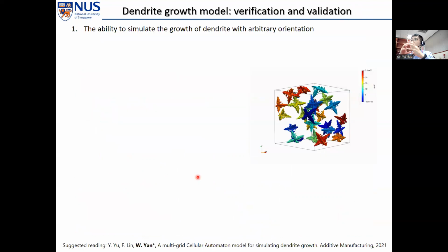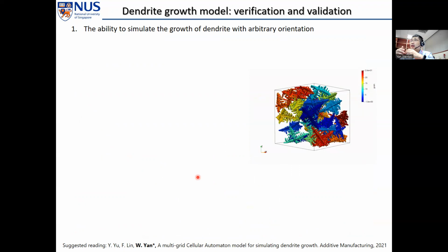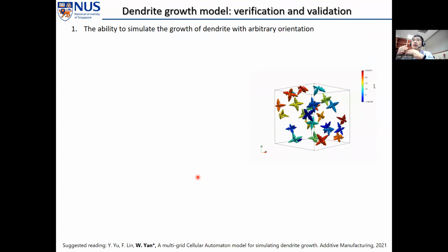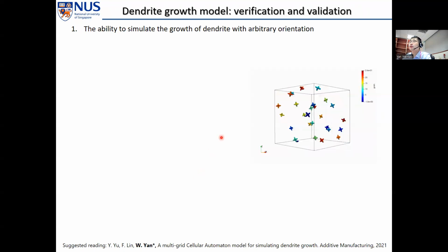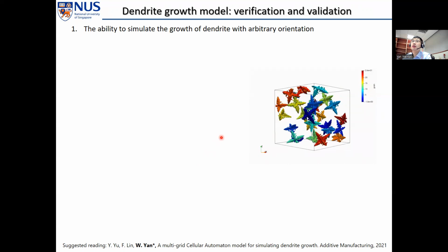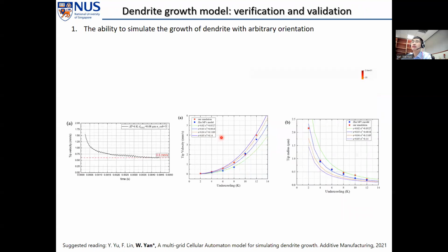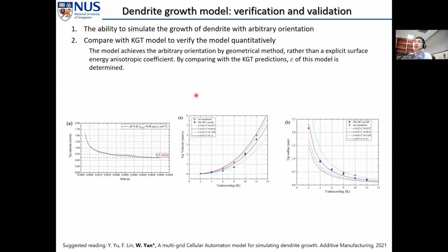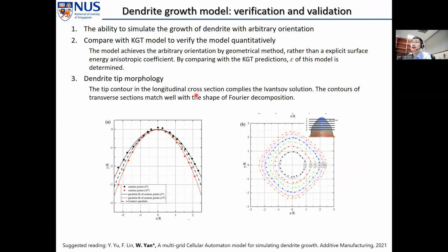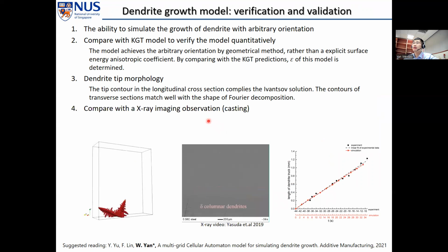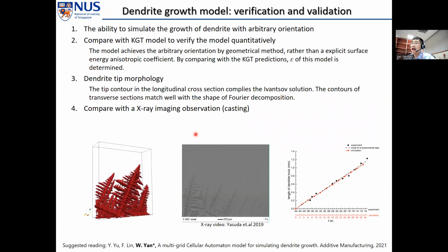But for even smaller scale, in dendrite scale, that is where the solidification defects happen. So to do that, we develop a new model to simulate the dendrite growth with arbitrary orientations. And then we compare this model against some classical models like the KGT model and LGK model. And then we compare with X-ray imaging results for a simple case casting.